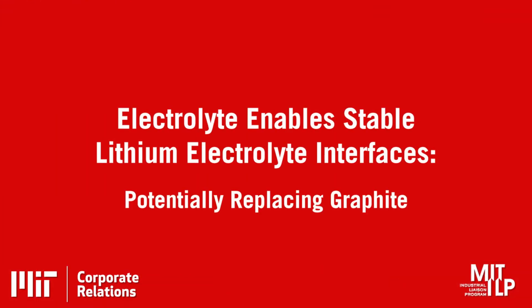And so together with some colleagues, Jeremiah Johnson as well as Julie, we have been able to develop new electrolyte solutions that replace the carbonate electrolyte and can essentially stabilize the electrolyte and electrode interface, enabling the use of a nickel-rich positive electrode. In addition, this electrolyte also enables reversible, stable lithium-electrolyte surface interfaces, so it potentially allows us to replace graphite with lithium. I think it is potentially one solution to significantly increase the energy of lithium-ion batteries.